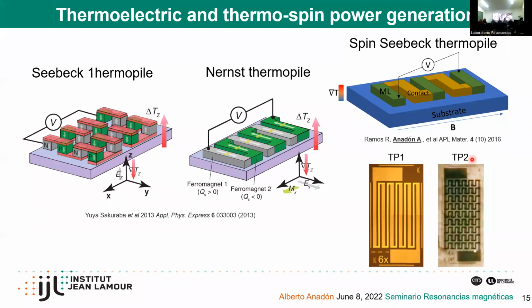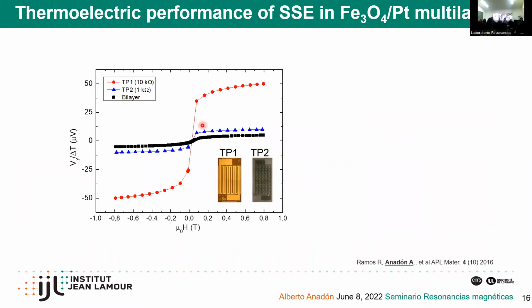And the other approach that we took was to use one of these devices in which we contacted this in series with different smaller terminals. Our guess was to have a higher output due to the parallel nature of all the spin current generated in the system. So this is the voltage measurement. In the first design, we observed that the voltage is increased by an order of magnitude. This is what we expected due to this different design of the device.